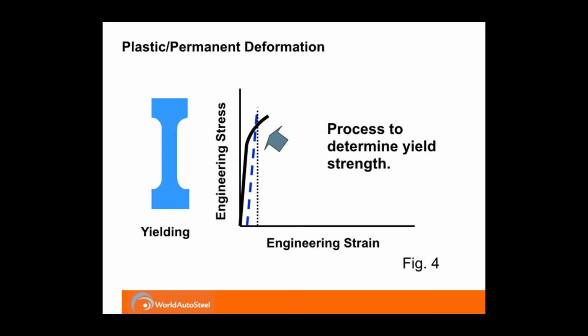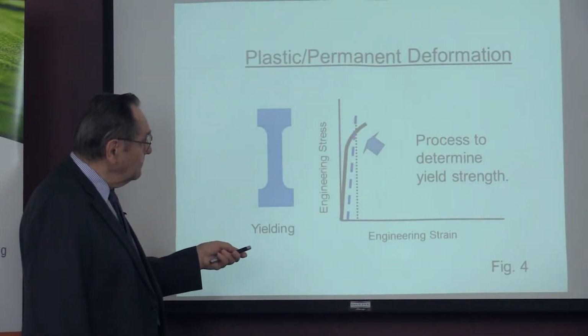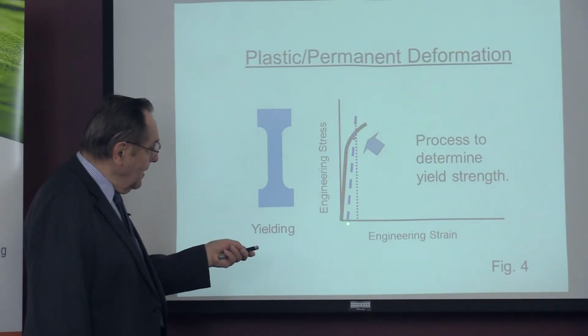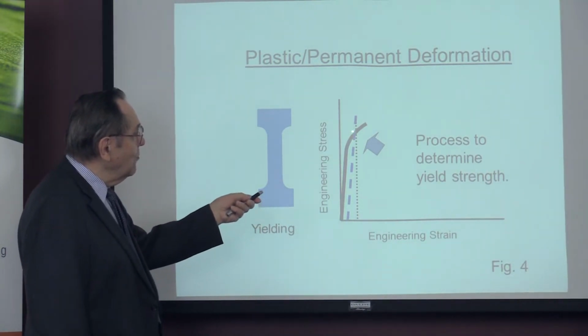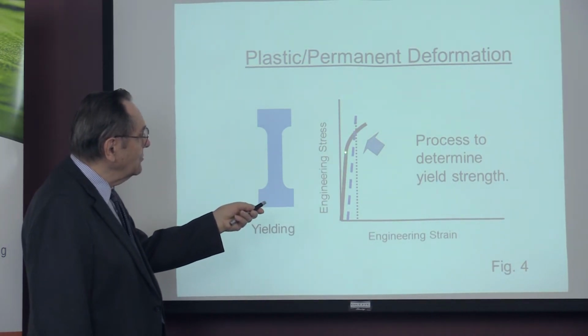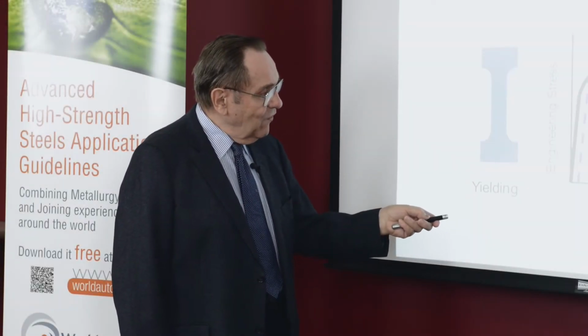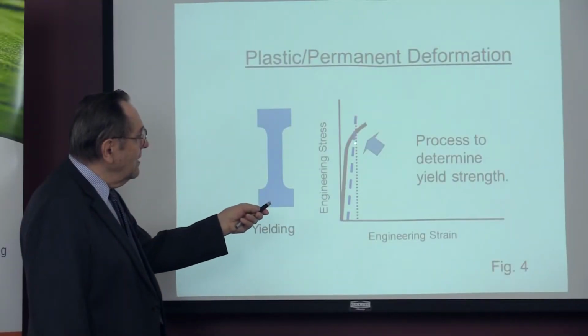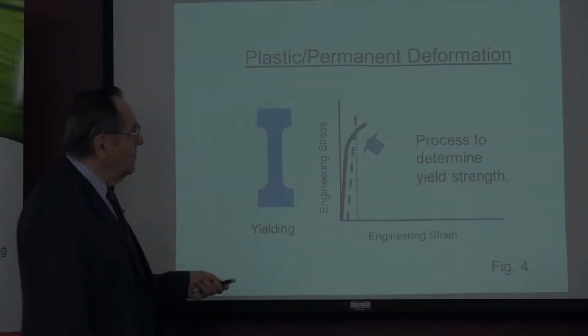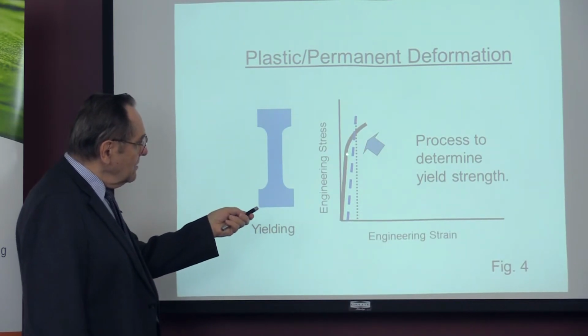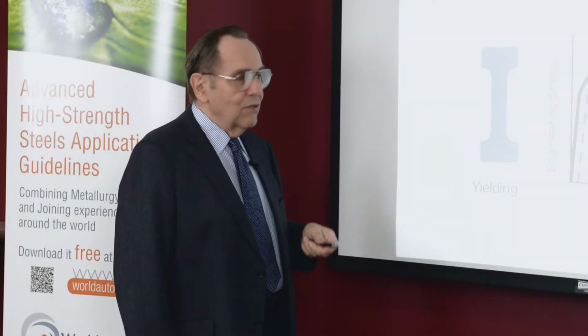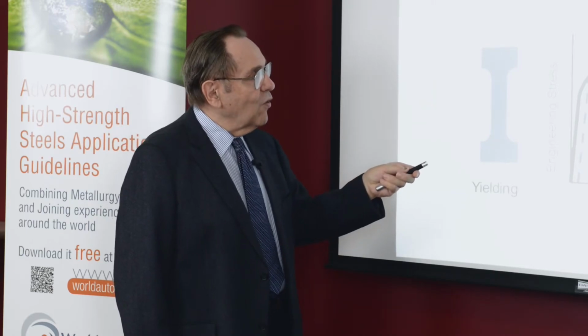Another way to determine the yield strength is to do a line which is offset 0.2% and take that line and draw it upwards, and where it intersects this modulus line is the yield stress. Other countries take a 0.05% strain, draw a vertical line, and where that crosses, that's the yield strength. These two ways are about the same for most of the metals, but that's how you determine the yield strength. This is in the elastic region. Now this has the plastic region plus the elastic region. You don't get rid of the elastic region when you're under force.